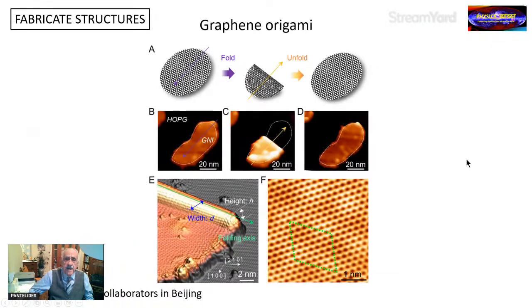Here I was showing you how the scanning tunneling microscope, in addition to pushing individual atoms around, can use the tip to pick up a piece of graphene. You can fold it over and then unfold it without any damage. This was first accomplished by my collaborators in Beijing in 2020. And you can see here, once you fold it, you have a nanotube-like structure.